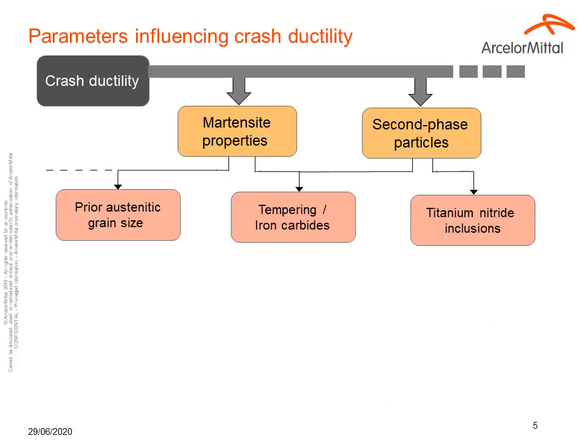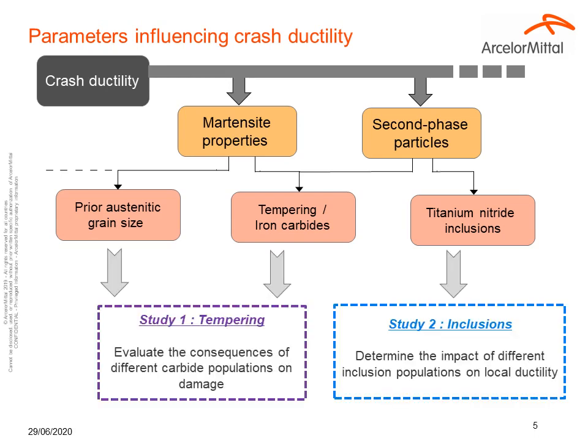In the martensite properties, you have the role of the microconstituent refinement induced by prior austenitic grain size reduction, and also the effect of tempering, which is linked to second phase particles due to the presence and the modification of iron carbide. In the second phase particles, you have the role of the titanium nitride inclusion. Likewise, we did two different studies. The first one is on the effect of tempering to evaluate the consequences of the different carbide populations on damage, and the second one is about the inclusion, and more precisely the titanium nitride inclusion, to determine the impact on local ductility.